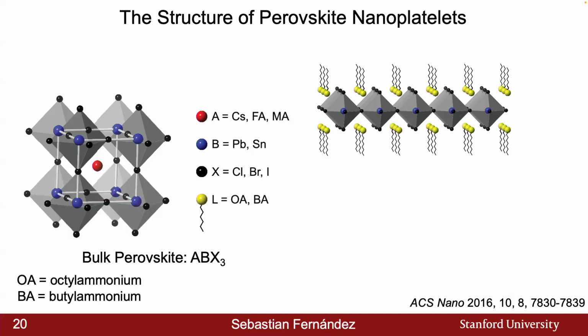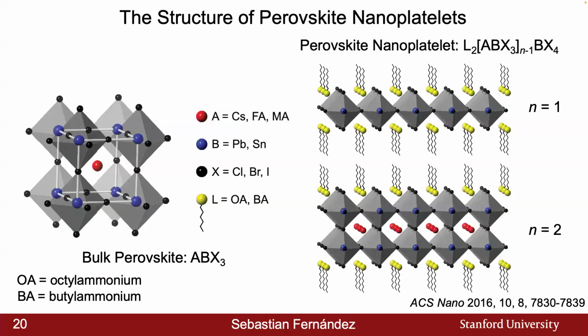So confining their growth in one direction, and therefore leading to formulas that look as follows, where L is again the ligand species, ABX3 is this bulk unit cell, and this n-1 is the thickness of the platelet in terms of that unit cell. So here we can see clearly that we don't have this unit cell within that first structure. And so this is actually the n=1 perovskite nanoplatelet governed by the formula L2BX4. However, if we start to have one unit cell, this would be the n=2 perovskite nanoplatelet. And we can keep going with this, but this will largely limit the discussion for this section here.